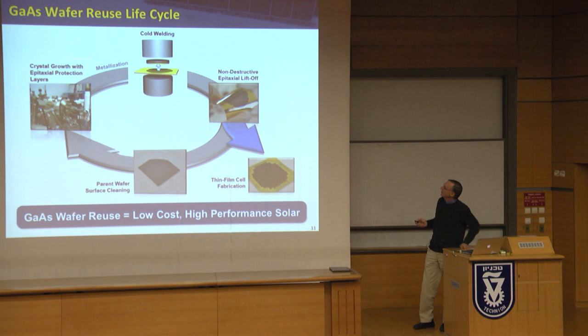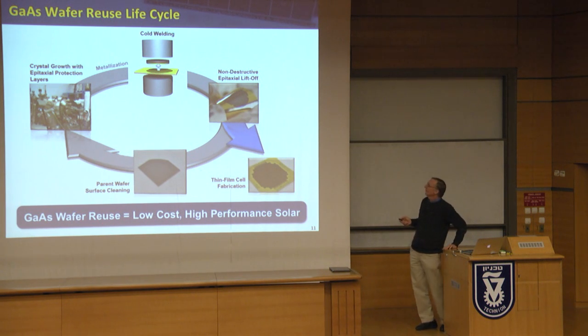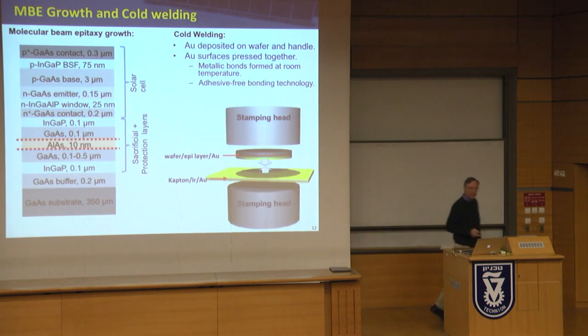We grow our layers. We cold weld bond the epi with the wafer to a plastic substrate that is coated with gold, very much like your sandwich bags or potato chip bags. We then peel off non-destructively the epi, leaving it on the plastic substrate. We process our cells. We take that wafer, we clean it without polishing, and put it back in the system, and do that round and round and round.